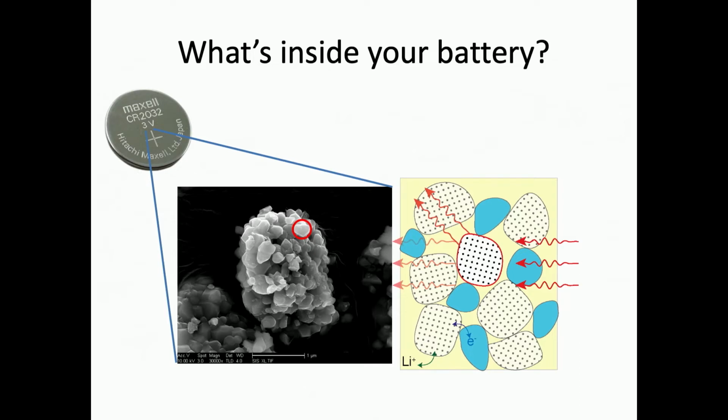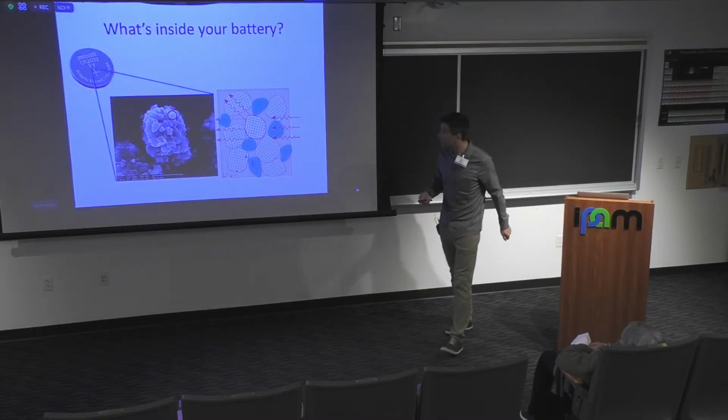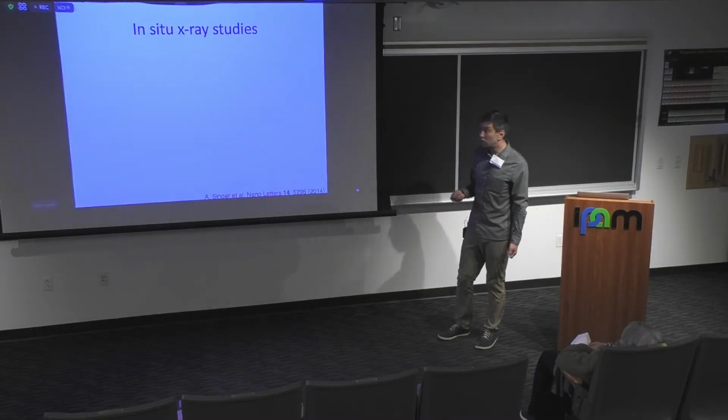And because we have a well-collimated monochromatic beam, similar to probably what you've already heard from Ian and others, we can basically satisfy the Bragg condition only for one of these particles and not all of the particles, and we can study a specific particle. That's basically the idea of what I wanted to show you.